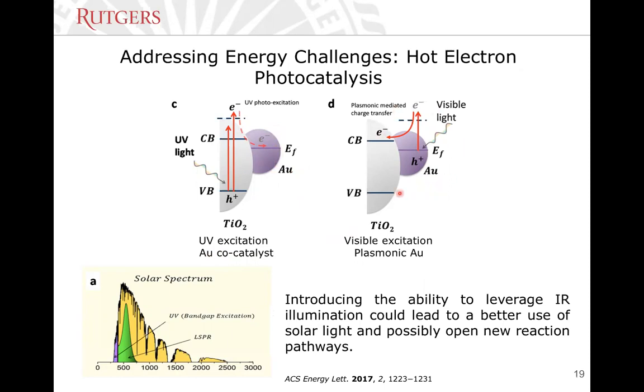What we actually are more interested in is the particle absorbing radiation through plasmonic resonances. And then once, as I said before, the electrons are higher up in energy, they can be extracted and transferred into the conduction band of the photocatalyst. Normally, however, what has been done so far is that this excitation looks at UV radiation. So this small sliver here is 5% of the solar spectrum. And if we look at the other spherical nanoparticles, we see that it focuses around 520 nanometers. So the high energy visible range. But what about all the rest of the solar spectrum? We are actually wasting it.